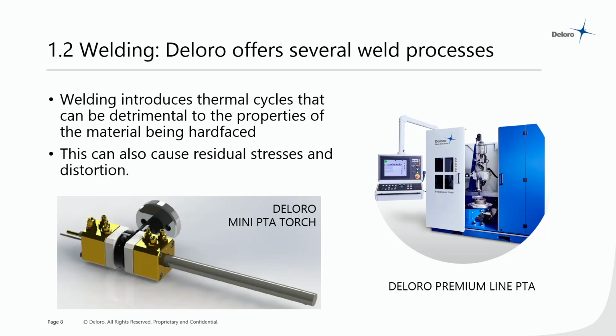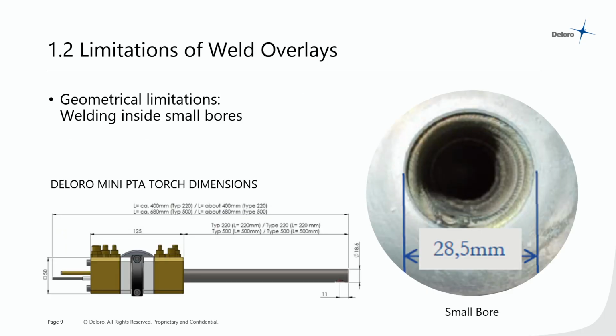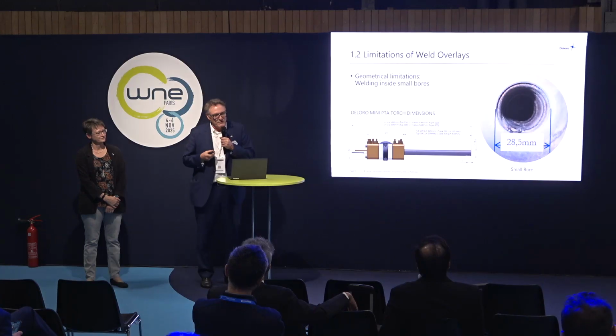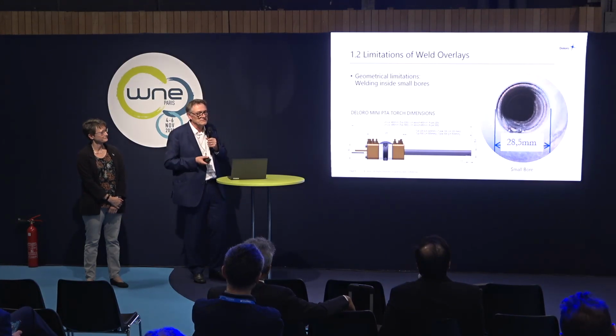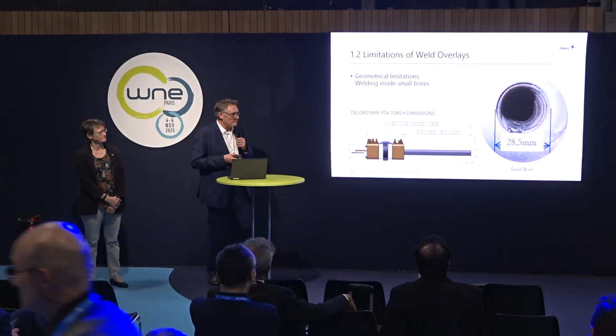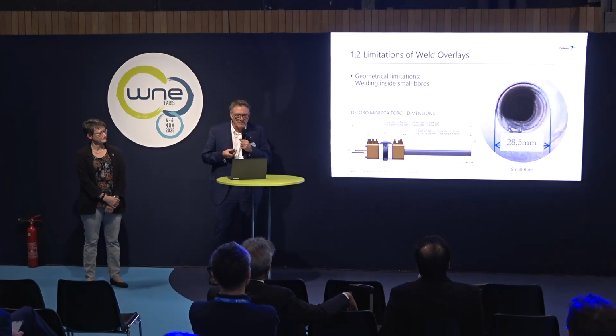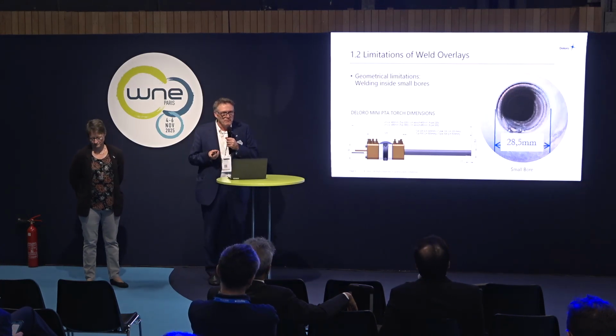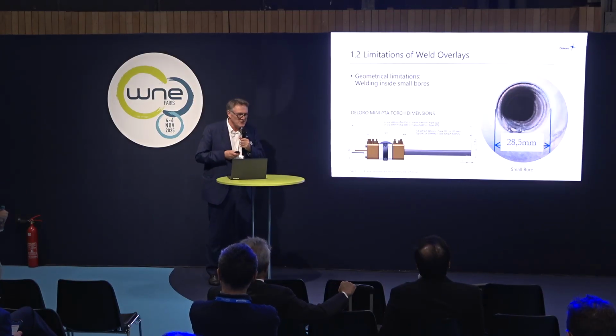manufacturing, we have at DELORO some welding applications like PTA welding, TIG or oxyacetylene. We also use laser cladding. We offer also PTA solutions, which are able to weld in internal diameters, in very small diameters as well. However, here we are facing also some challenges. For example, if we need to go in a very small diameter, in a deep bore, with the cladding we are facing thermal cycles, residual stresses, distortion, and some special torches we have in our portfolio need very special training to use them. And sometimes we also have bores which are much smaller than 25 millimeters and very deep in the material.